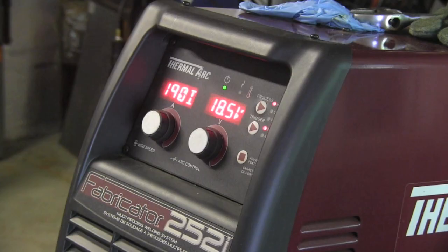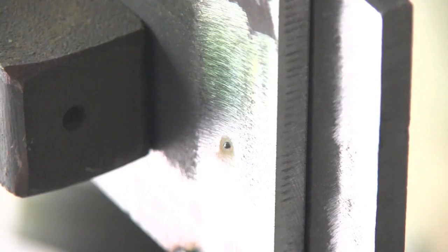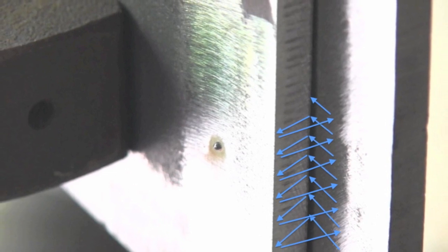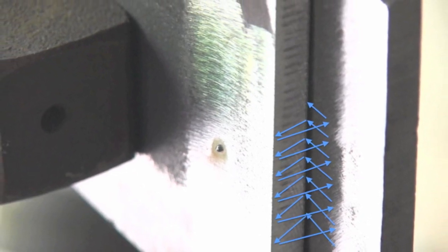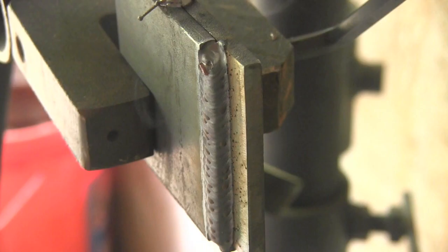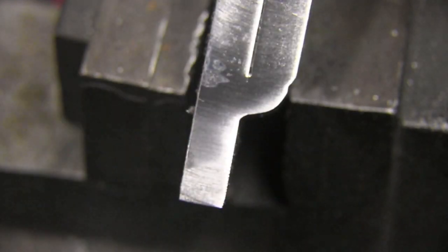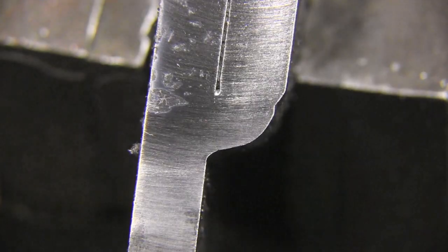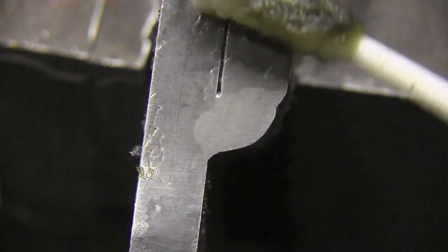All right, now I'm going to turn the wire feed speed down a little bit and clean the metal. I know that the crown was a little high, so I tweaked the wire feed speed down a little bit. Same technique again. This time, everything clean to nice, clean, bright metal. And you see I'm even kind of hiding the puddle a little bit with the cup, not intentionally, but I'm just trying to keep my stick out short. And I'm picking up my travel speed just a little bit, but still trying to stay on the very front of the puddle. And that made for a better looking weld with a little bit less crown. Well, let's see what that did. The acid will tell the story.